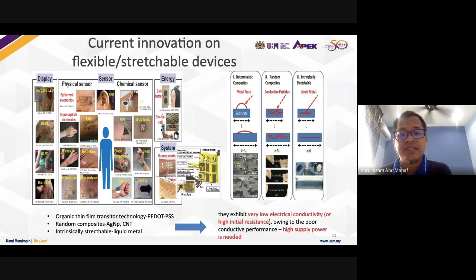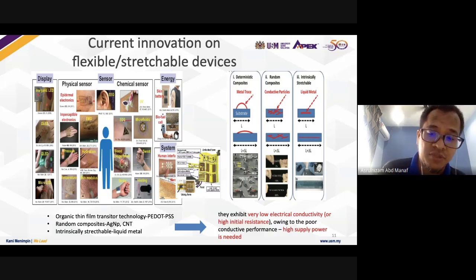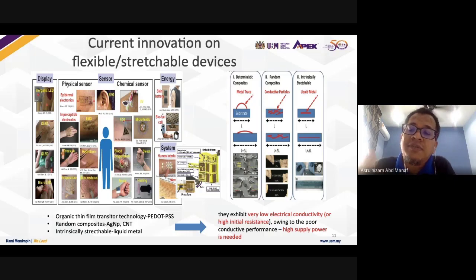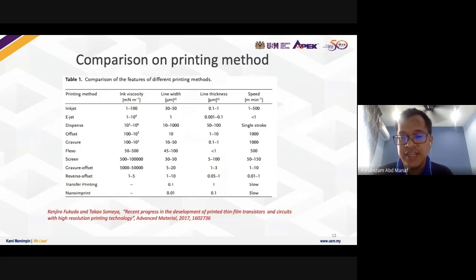conductivity, as a baseline to a copper thread, similar to the PCB that is commonly used in our printed circuit boards. But of course, to reach a similar 10 power 6 like the PCB is really difficult. So we try at least 10 power 4. That is sufficient based on the application. If you want to make an antenna or any inductive device, it must have highly conductive materials, a highly conductive ink. Right?